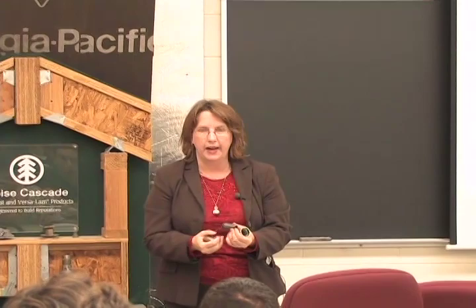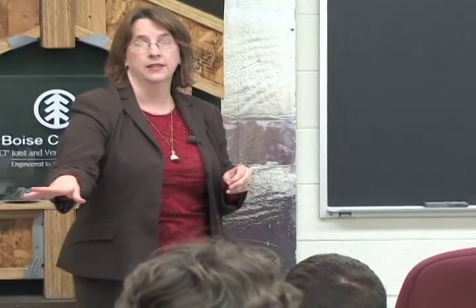They're going to get the forms all ready, and then they're going to put that 35 or 40,000 psi of pressure on it, and they'll use one of these strand chucks. It's got a little O-ring in here with little teeth that will actually hold that strand with all of that pressure while the concrete is curing. So you can kind of see what that looks like. And you'll see in the plants that they're all just as clean as this one is.